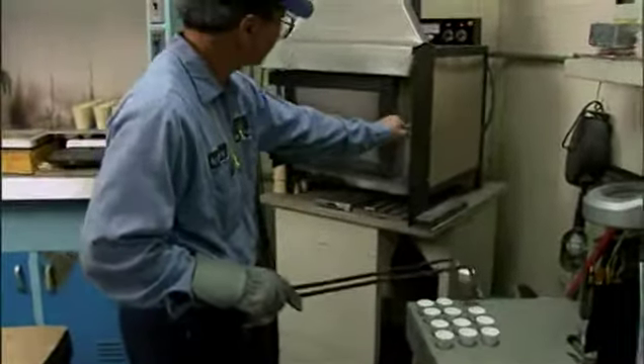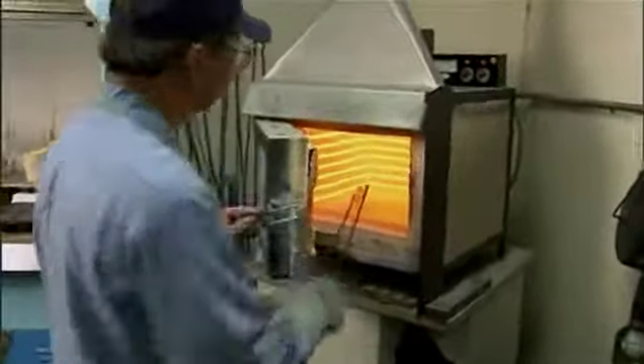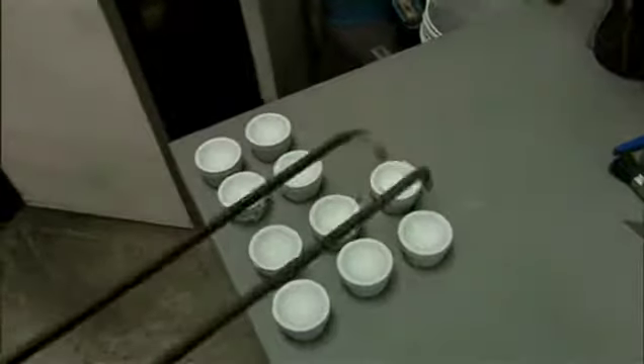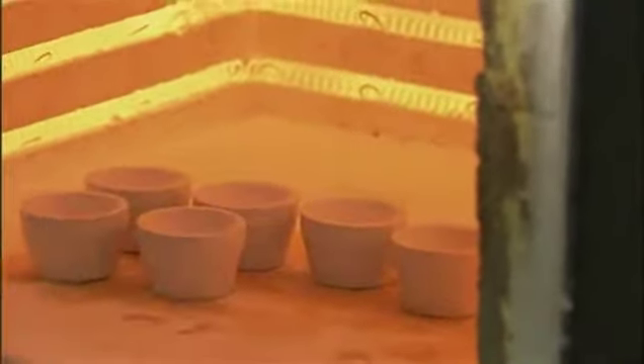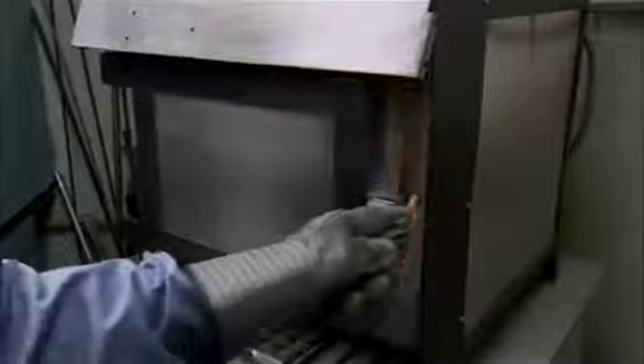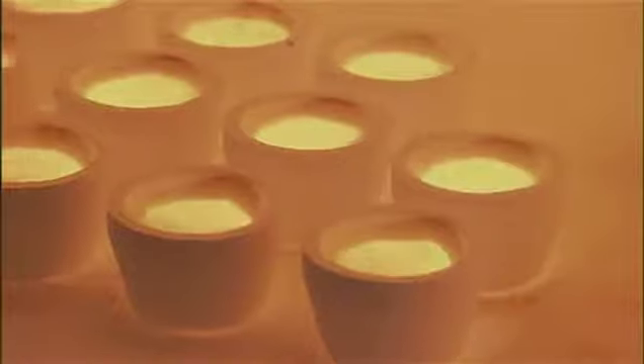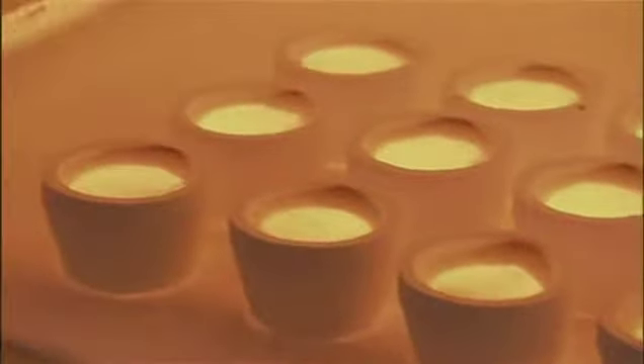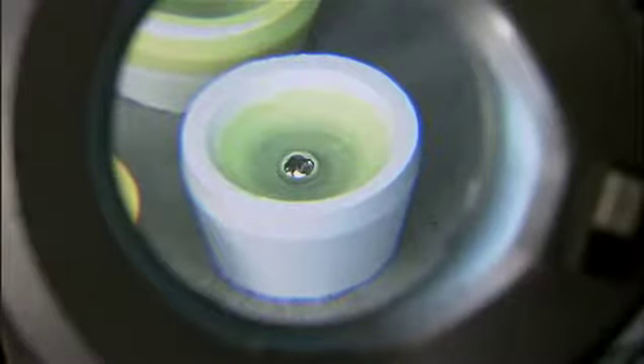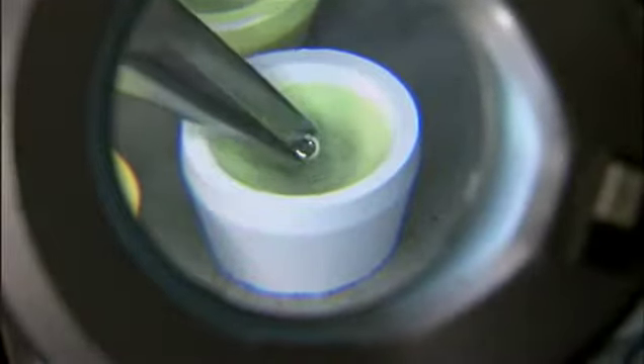The muffle is recharged to 1600 degrees and filled with a smaller dish called cupels. It's a bone ash mixture, hard pressed. They're very absorbent. We'll put the lead buttons into those cupels. We will leave those in until all of the lead has been evaporated. All that's going to be left in there is going to be total precious metal. We'd call that a TPM.